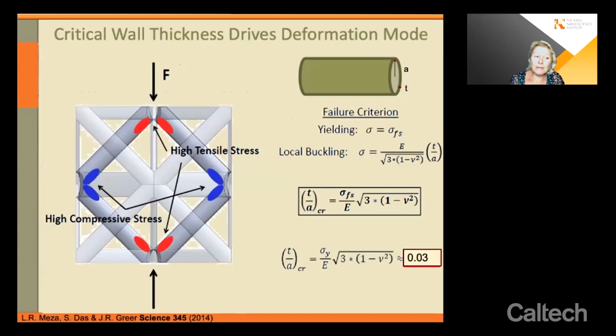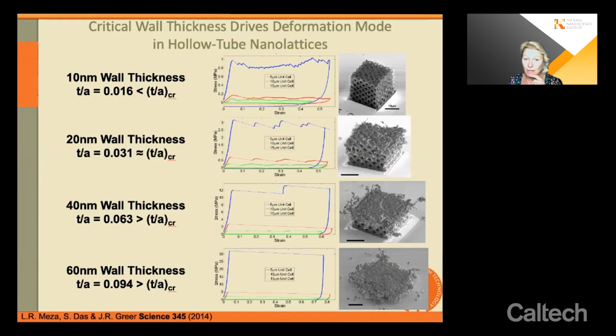I would like to point this out. It turns out that the hollow architectures recover because, since you asked, you guys are going to have to endure some math here. If you imagine a beam having a particular thickness T and a radius of A, it turns out that there is a critical ratio of T over A that's unique for each different material. If your architecture is designed such that your T over A is below this critical ratio, it will undergo a buckling elastic instability. But if it's above this ratio, then it will fail. And sure enough, this is what we're observing with the hollow architectures.